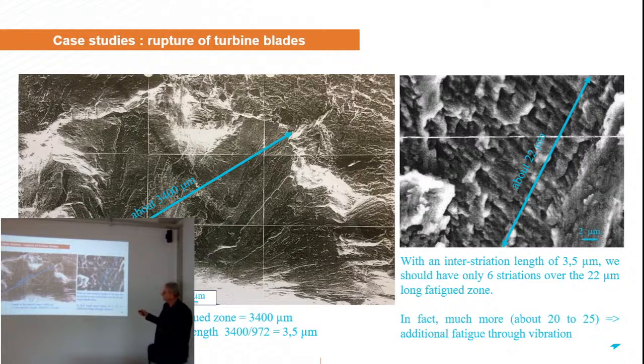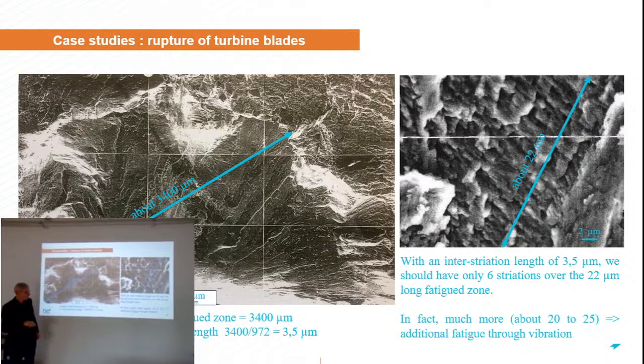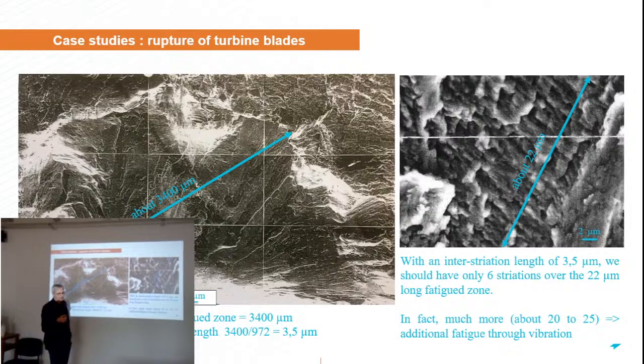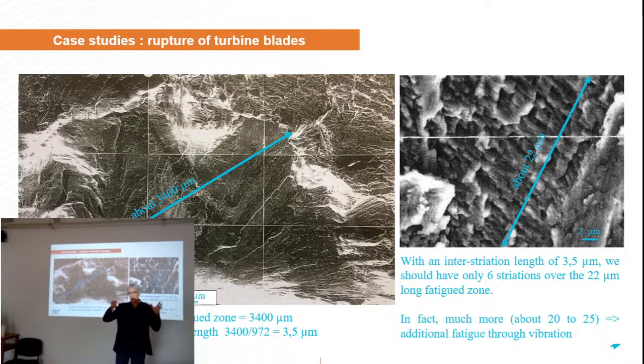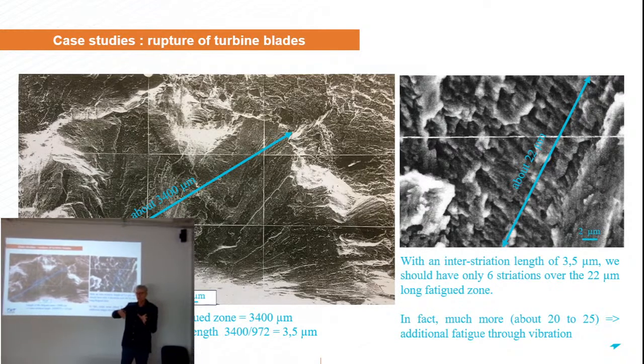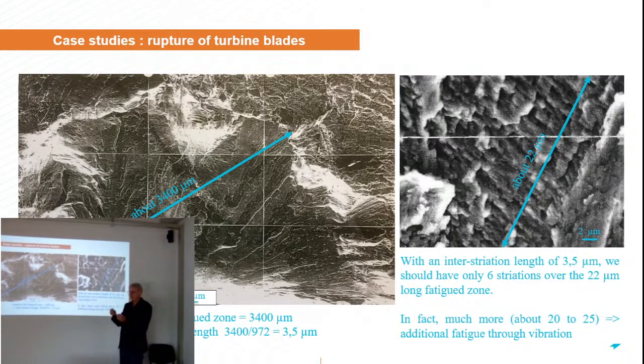So the conclusion for this case study was to say that probably there was an additional fatigue loading in addition to the nominal loading, which was considered as vibration. So you have the nominal fatigue loading plus some vibration because the blade was not mounted on the disc properly. So vibration plus fatigue loading makes the fracture of the material occur earlier than expected.